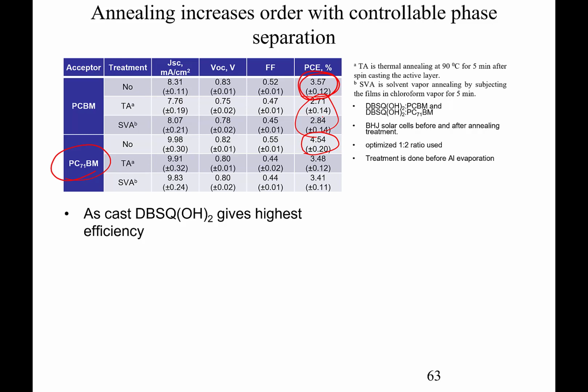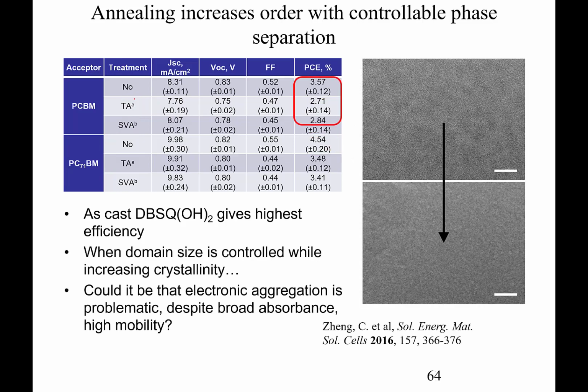we've even done some solvent vapor annealing and different thermal annealing to try to increase the packing structure so that you increase the crystallinity, but maintain small domain sizes. Well, there's a lot going on here in these devices, and basically the as-cast films seem to give us the highest efficiency if we can control the crystallinity while keeping the domain size small. We seem to be doing okay, but we still have too many questions in our group at the moment, too many questions that are unanswered because of the complexity of these systems.